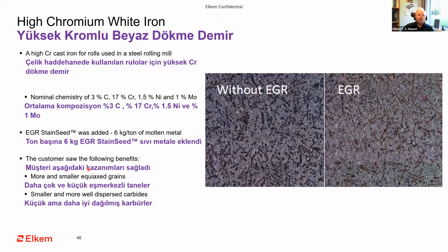Okay, first, high chromium white iron. So far we have only one case study we can show off. This is a high chromium cast iron for rolls used in a steel rolling mill. The nominal chemistry of this grade was 3% carbon, 17% chrome, 1.5 nickel and 1% moly. And then EGR stain seed was added at 6 kilograms per ton of molten metal. And here you see the microstructure in the castings without EGR, and this is the one with EGR. What the customer saw was more and smaller equiaxed grains and smaller and more well-dispersed carbides. So we saw everything we wanted to see in these high chromium white irons.